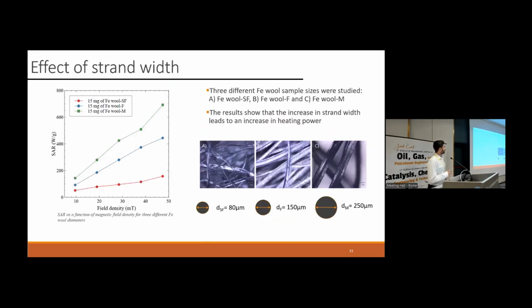The first thing that we wanted to study was the effect of the diameter of the strands of Fe wool on the heat. So commercially, we found these three different types of Fe wool: the super thin one, thin, and medium. And here we have the average diameter of the different samples. And as you can see, the bigger the diameter is, the more heating we can have. For example, for the biggest one, we have around 700 watts per gram, the maximum value of SAR that was measured. And for the super thin one, we have around 160 watts.